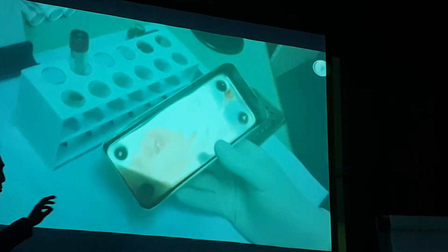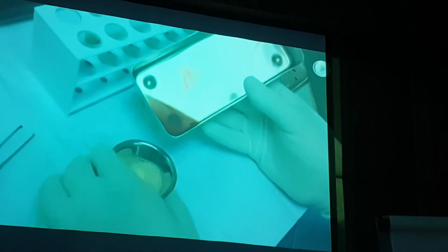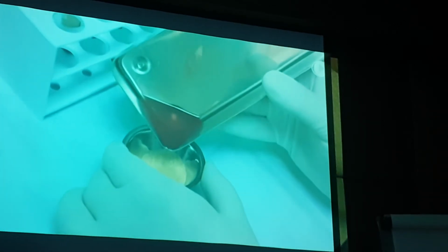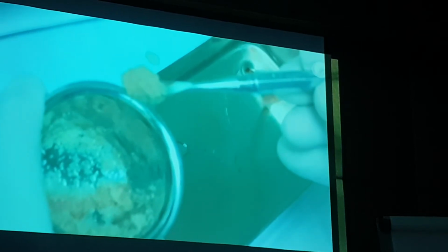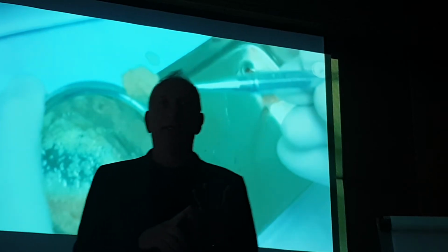But it's good. If nothing else, it's great. So this is the serum that we've collected after squeezing out all the fiber, and we'll demonstrate this tomorrow. We're going to hydrate our graft materials. The great thing about this is that it's not that it makes sticky bone, but it makes the particulate sticky, which means that when you pick it up with your instrument and you carry it, it doesn't fall off your instrument, which happens when you use saline. And the reason it doesn't is because it contains 3 tissue adhesive proteins: thrombospondin, vitronectin, and fibronectin, which are adhesive proteins.